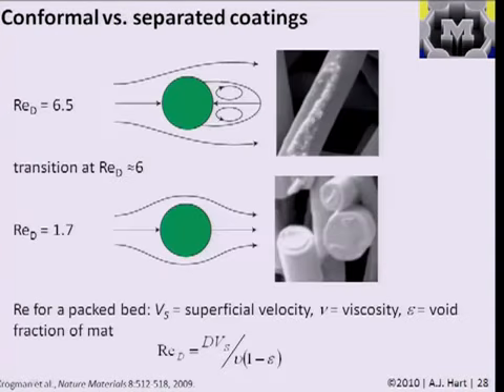And it turned out that the flow dynamics of the solution, the spray that they were putting into the membrane, in fact determined if they deposited a conformal layer as was desirable, or a layer which was not continuous and just had kind of this bead of material at the back surface. And they were able to relate this to the fluid dynamics of the problem, for example, by calculating the Reynolds number based on the diameter of the fiber. And this was an expression for the Reynolds number that's based on flow through a packed bed. They considered this fiber to be a packed bed of particles with a particular diameter d.